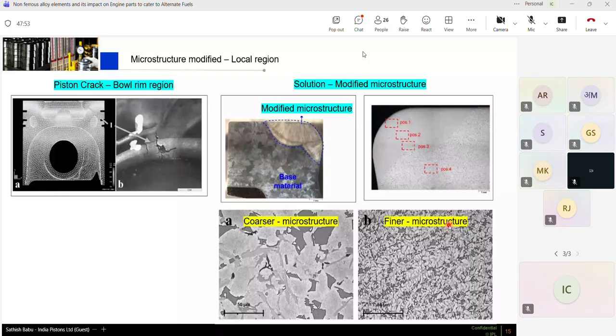So when we started focusing on this hydrogen engine development, where very high heat release was happening inside, we saw a lot of technologies coming up. In our case, as I told, we also manufacture very high-end technology pistons, which should reduce the temperature of the piston and try to maintain a good amount of element percentage to meet the customer target. And still beyond that, a fuel like hydrogen will demolish this piston in a very easy way, like making pits. As I said, pitting marks and corrosion marks get created, and it will spoil the complete microstructure of the part.